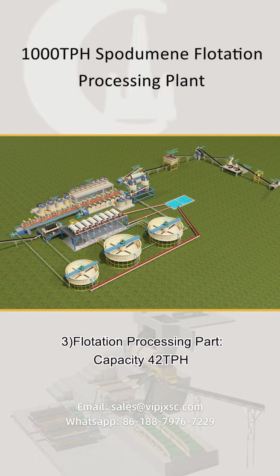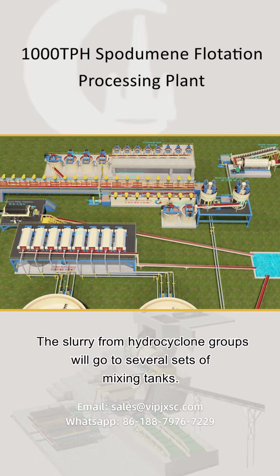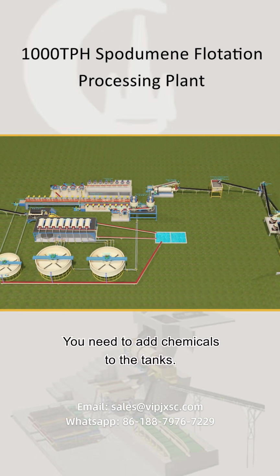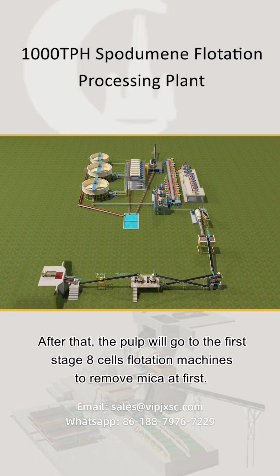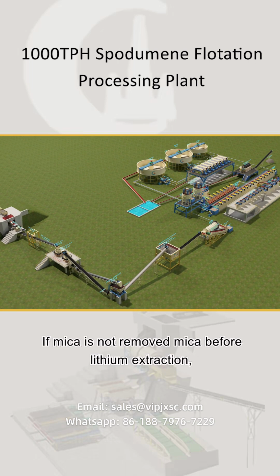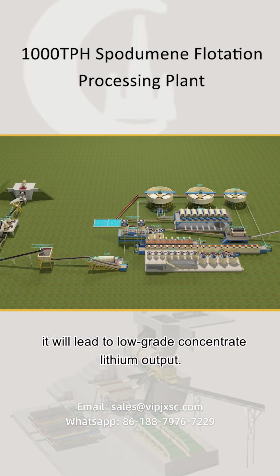3. Flotation processing part. Capacity 42 tons per hour. The slurry from hydrocyclone groups will go to several sets of mixing tanks. You need to add chemicals to the tanks. After that, the pulp will go to the first stage 8 cells flotation machines to remove mica at first. If mica is not removed before lithium extraction, it will lead to low-grade concentrate lithium output.